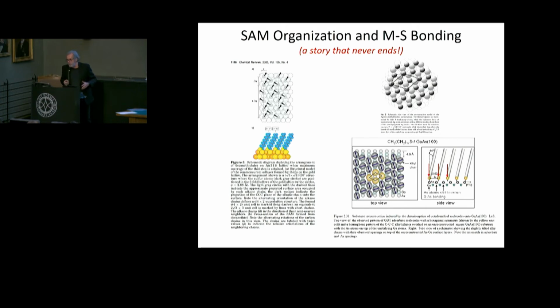And as you go up to things like silver, it turns out that's a different overlayer, and that overlayer actually reflects assembly on top of a sulfide interface, because the substrate actually activates the molecules. It's not assembly on the metal itself, but assembly on a monolayer level metal sulfide that has a root 7 characteristic structure, so I'm speaking in jargon here. And then you can go to things like the picture on the bottom right-hand side, the characteristic structure associated with assembly on gallium arsenide 100, which is a much more complicated substrate to deal with, and so on and on, and people have worked this out in grisly detail in the literature.